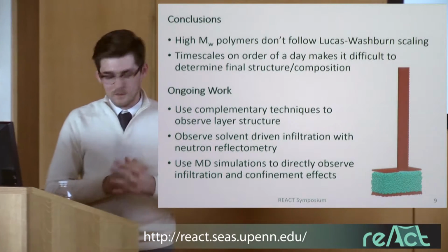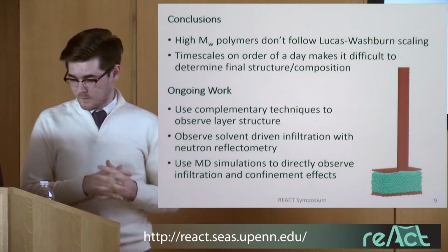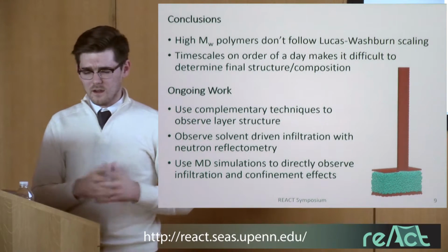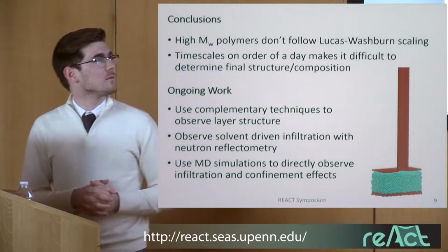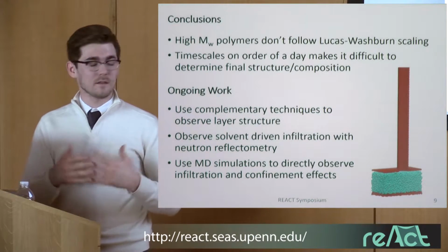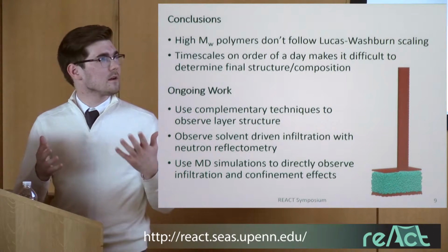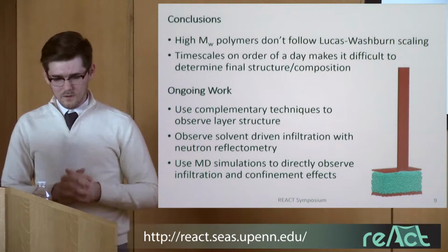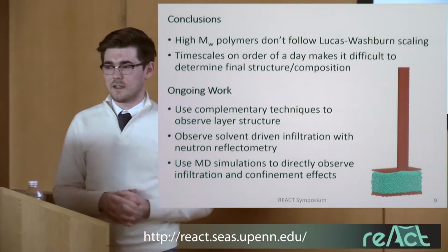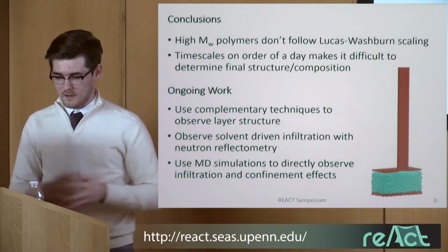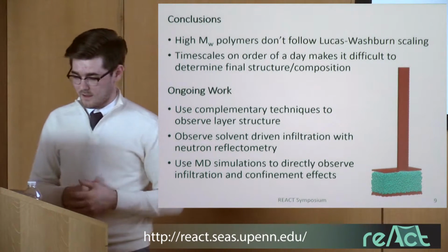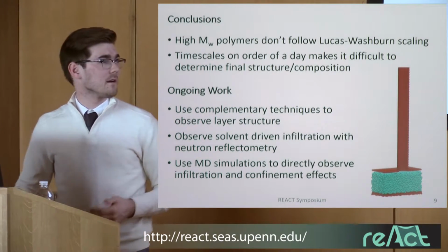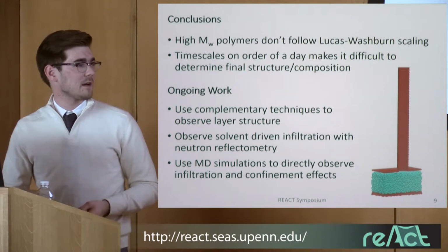I'd like to conclude by saying that I've been able to show that high molecular weight polymers don't follow Lucas Washburn scaling. One issue that comes up in the data is that it's not clear whether infiltration has stopped yet. So the ongoing work that would be important is to use complementary techniques in order to observe the final layer structure. And as Neha has shared with you, she is working on solvent-driven infiltration and would like to observe that process with neutron reflectometry.